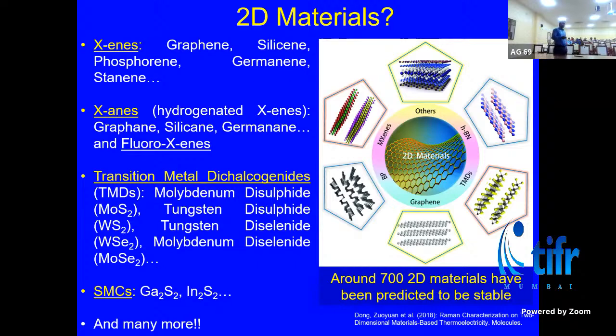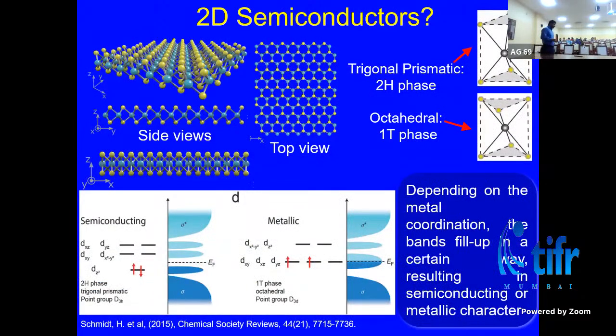If I categorize the range of 2D materials, graphene falls into the family called X-enes. Then you have phosphorenes, hexene, all in the X-enes family. We work on graphene and phosphorene. Then you have X-anes, and then you have transition dichalcogenides. These are basically the chalcogens of transition metals, like sulfide and selenide of molybdenum and tungsten, and these are basically semiconductors. And then you have 2D insulators like boron nitride. What we work on is graphene, which is a 2D metal or 2D semi-metal, phosphorene, transition dichalcogenides, particularly these 4 TMDs, and hexagonal boron nitride, which are 2D insulators. And for any practical electronic, optoelectronic device system, all you need is a metal, semiconductor, and insulator. So that was graphene.